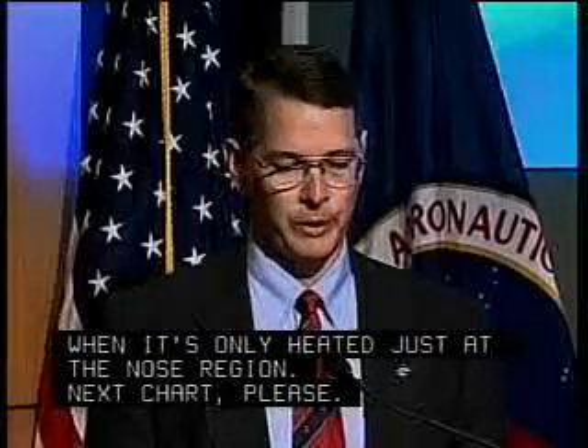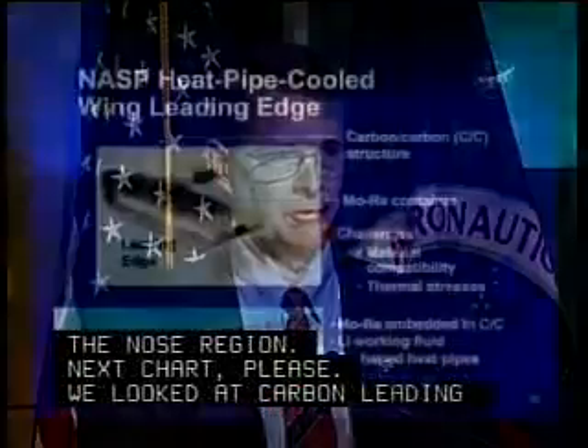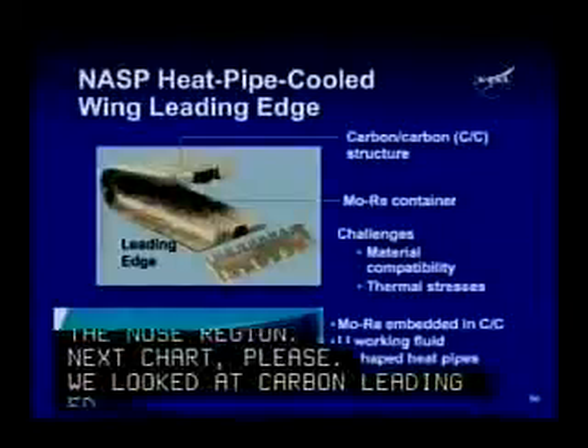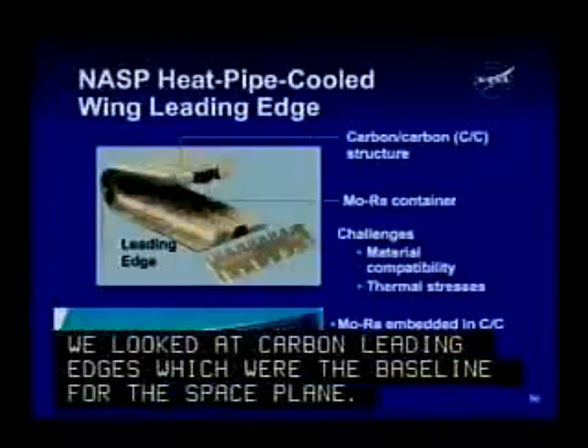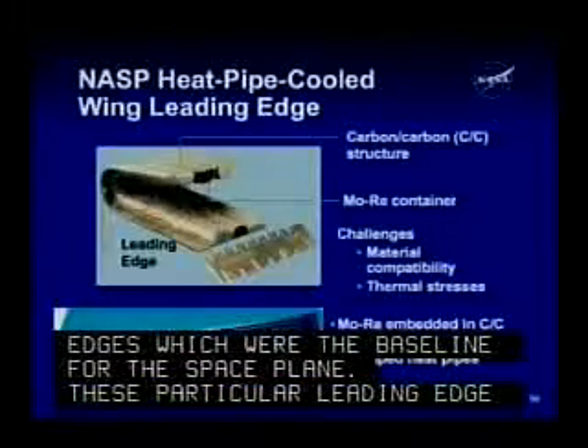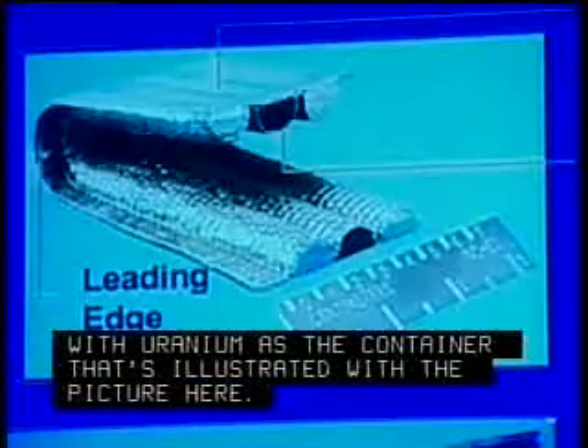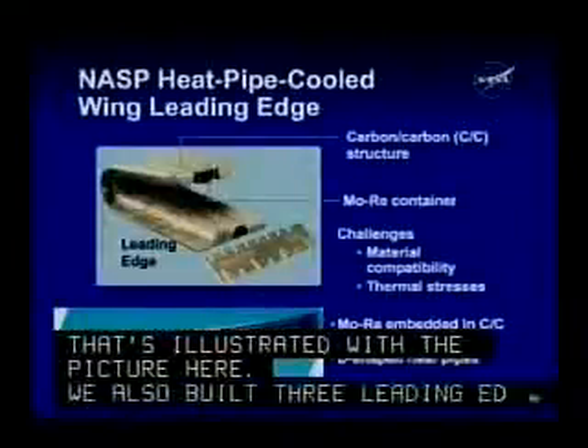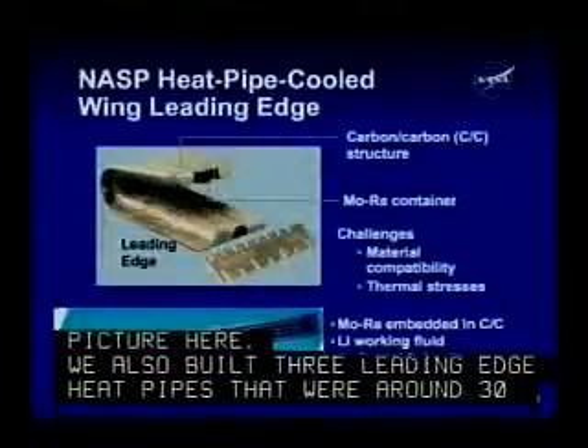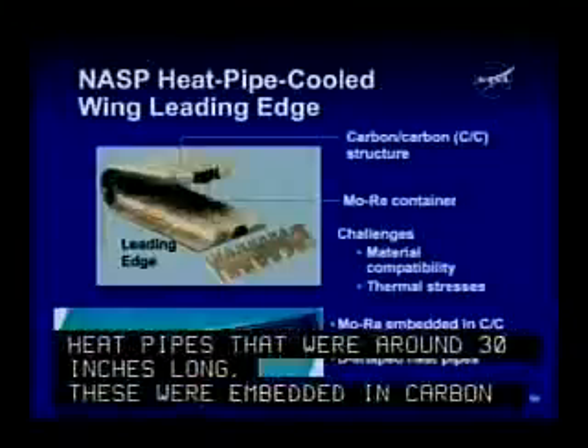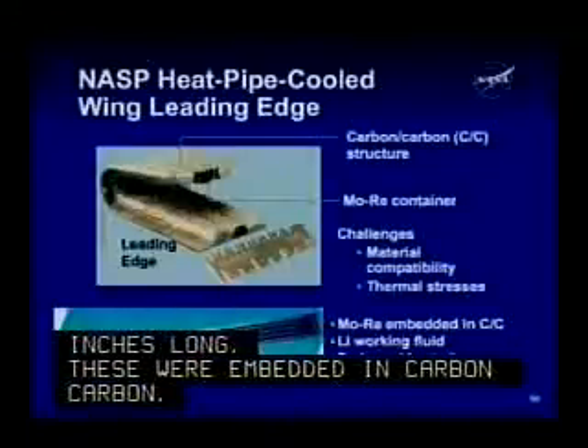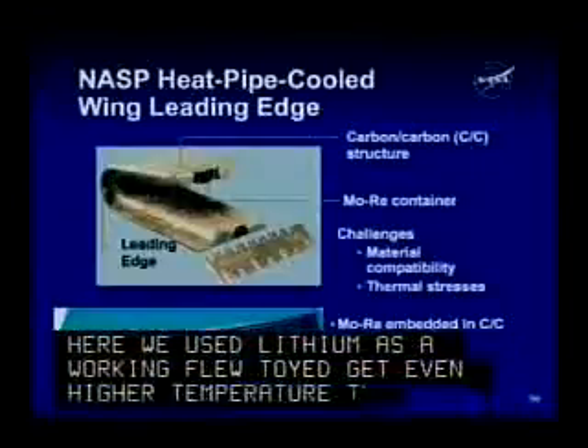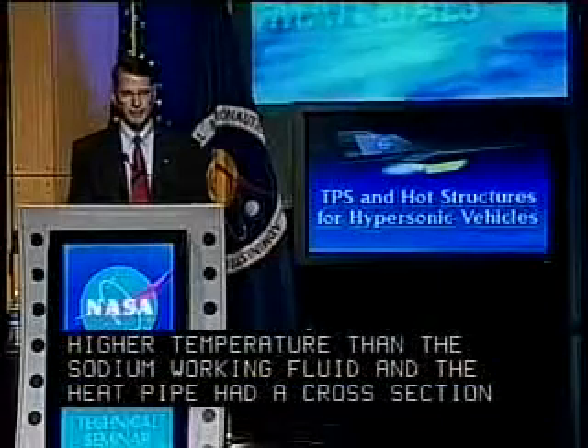Okay, during NASP, we looked at carbon-carbon leading edges, which eventually were baseline for the National Aerospace Plane. These particular leading edges had carbon-carbon structure with molyrhenium as the container. That's illustrated with the picture here. We also built 3 leading edge heat pipes that were around 30 inches long. These were molyrhenium embedded in carbon-carbon. Here we use lithium as the working fluid to get even higher temperature capability than the sodium working fluid. And the heat pipe had a D-shaped cross-section as shown in the top figure.